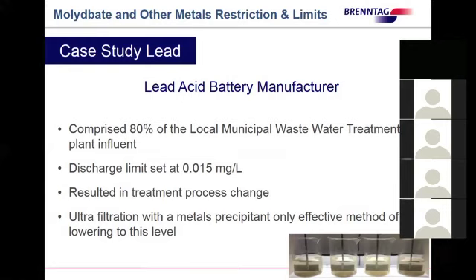So one way that we went about correcting that problem was we looked at the use of an aluminum chlorohydrate iron blend, and I tested that in the lab using the same porosity membrane filter, added the ACH at a desired treatment range, and measured how fast I could pass 100 milliliters of water through that filter. I also did it with just the metals precipitant present, and I did it with untreated water. And the result was that, in fact, the ACH gave us better and faster flux rate, and so we moved to that. And that was very helpful in keeping the plant running, because at the time they were actually having to haul their waste stream off the premises because they could not keep up with the influent.